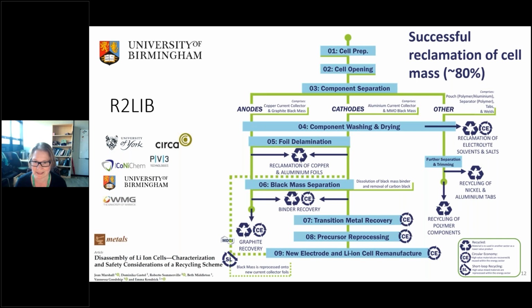So we open the cell, we stabilize it, we start to separate out those components, the anodes and cathodes. We can then delaminate the anodes and cathodes coatings off of the current collectors and then reclaim aluminium foil and copper foil. We're then left with a black mass. In this case, we have a graphite black mass, which is mostly graphite, and we have a cathodic black mass, which is mostly the layered oxides, which contain lithium and the transition metals. We can then process the graphite to reuse back in the battery again, and we can look at processing the cathode as well to directly reuse back in the battery again. Or we can use hydrometallurgical routes to recover the transition metal salts for remaking the cathode material.